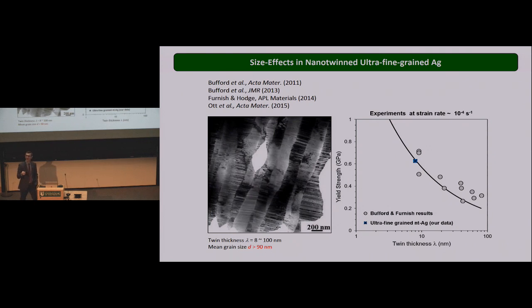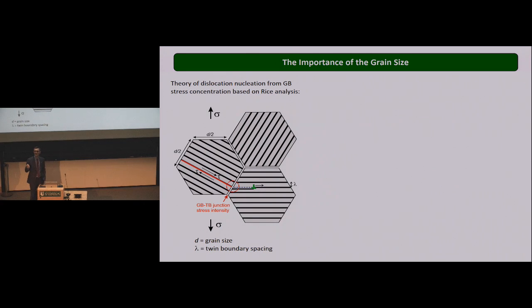But the problem with nanotwin silver is you can use the best technique, the best approach you want. You never get down to a grain size that's below the order of 100 or 200 nanometers, and a twin spacing below the order of 7 to 8 nanometers. And that's a kind of a problem because all the interesting mechanics happens just below that limit. The problem is we cannot make those materials to look at them fundamentally, right? And so the grain size is extremely important in this problem.